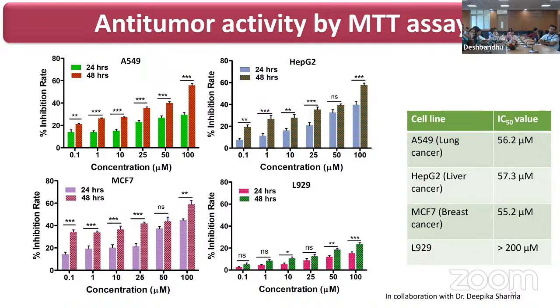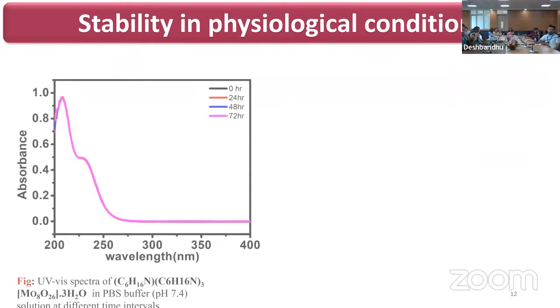We used the cell lines A549, HepG2, and MCF7 to assess the cytotoxicity, and we observe that as we go on increasing the incubation time from 24 hours to 48 hours, our solid exhibited very good cytotoxicity against the cancer cell lines. For any compound to be used for biomedical applications, we have to check its stability in physiological conditions.